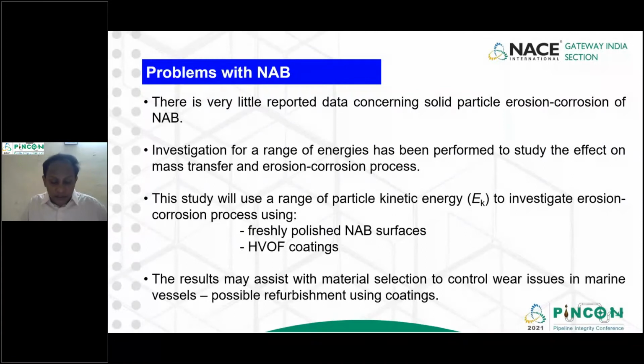In this particular research, I took a nickel aluminum bronze, and I will talk about the composition shortly. I studied mostly flow corrosion, erosion, and erosion corrosion behavior, and I compared it with an alternative, which is actually a coating. The coating was achieved using the HVOF coating, the high velocity oxy-fuel process. In that, I coated this nickel aluminum bronze material on the surface of mild steel to achieve the cast NAB property. As we go through the presentation, we'll see how it behaves.